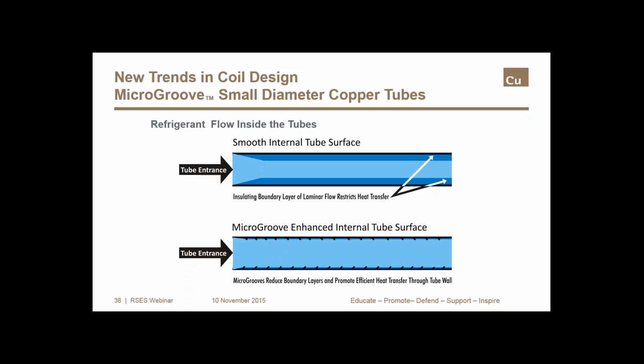Now the internal enhancements in microgroove tubes, in other words, the grooves and patterns that tube manufacturers put on the inside tube wall, they reduce this boundary layer and they increase heat transfer through the tube wall. You can see the boundary layer in a smooth tube develop and it does not dissipate or go away. But in a tube with microgroove enhancements, the boundary breaks down as it moves over the grooves. Then there's additional mixing of refrigerant that occurs inside the tube because of these grooves, and that also increases the amount of refrigerant that comes in contact with the tube wall. All of this improves the transfer of heat through the tube wall.